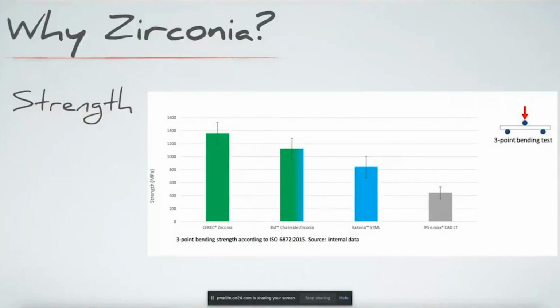But how strong is strong enough? And I think once we start getting close to 1,000 megapascals, I don't know that I'm getting much difference in the mouth from a 3M Chairside Zirconia in terms of fracture resistance or something like that compared to the CEREC Zirconia. But what I am getting is a lot more aesthetics than I would get with that really opaque Bruxzir type of Zirconia.